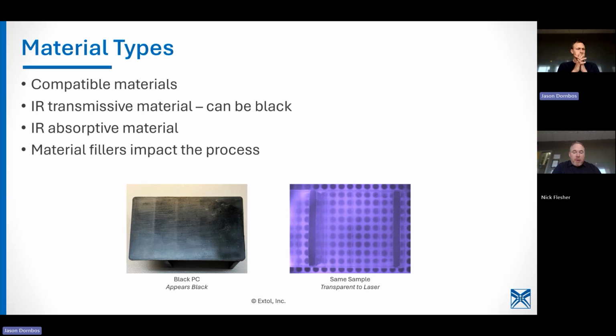Okay, so let's talk a little bit of material. We always get questions about material. We're at 30 minutes, so we understand we're getting to the end, so we're picking up the pace some. You can get visually opaque but transmissive to the 1 micron wavelength in certain resin types. This is polycarbonate. This is the same part. We have a laser inspection system where you can see that there are 2 weld areas. So you still get that opaque look. You can't really see the weld, but the laser transmits right through it.